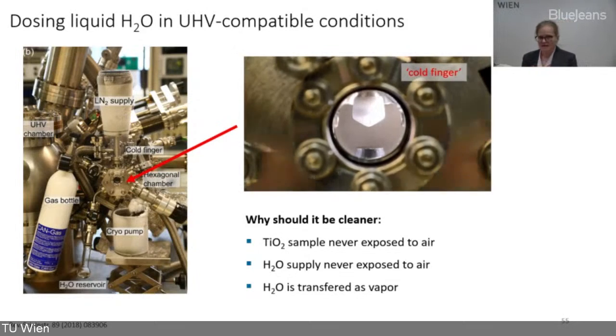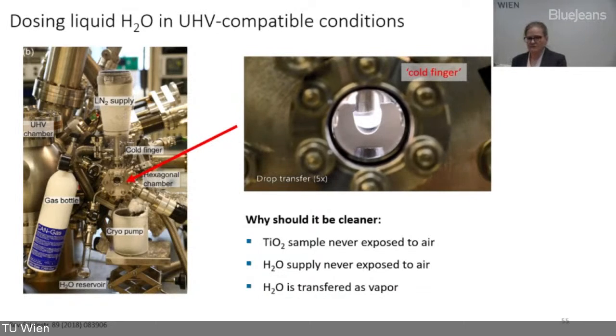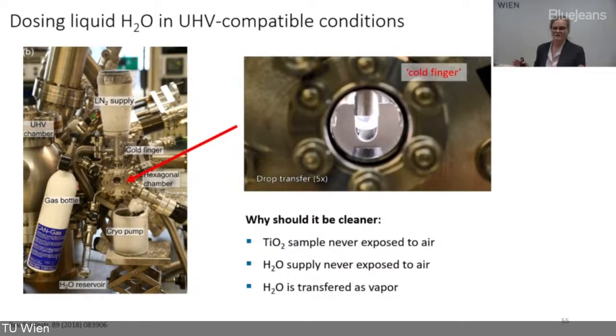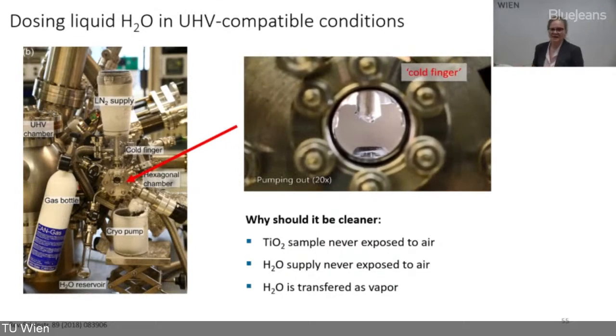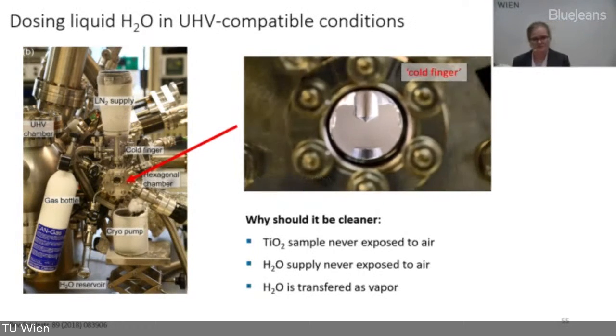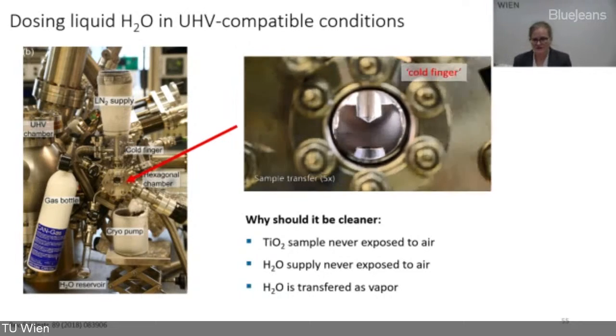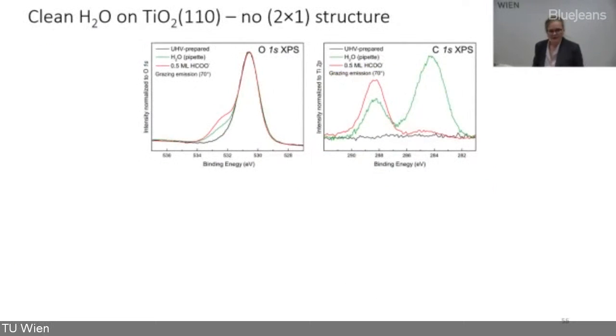Sometimes the ice melts and the water drops down on the surface, and then we let it evaporate, we pump out, and at some point take the sample back out again. So this should be way cleaner because the TiO2 sample has never been exposed here, the water has never been exposed here, and the water is transferred as a vapor. And sure enough it is.